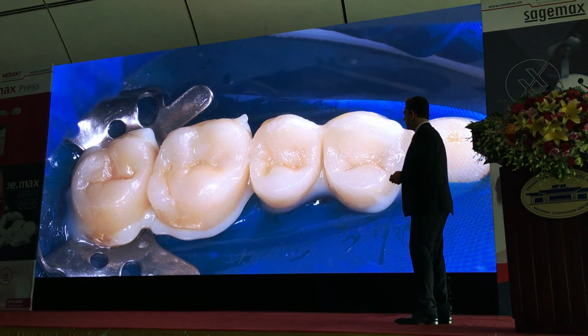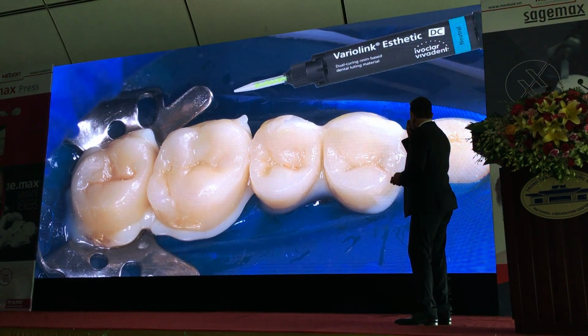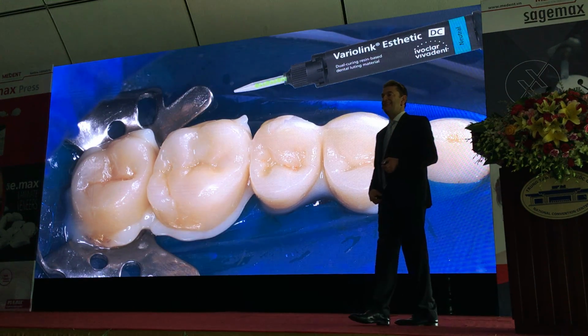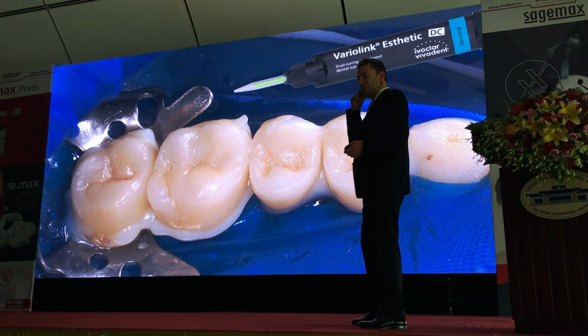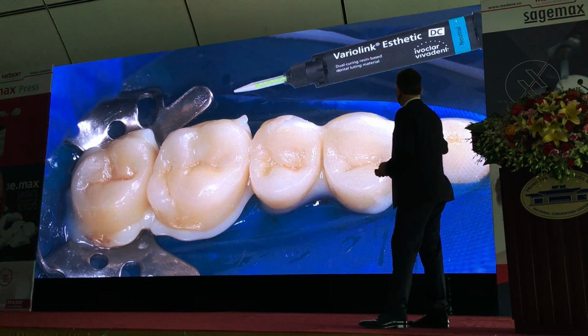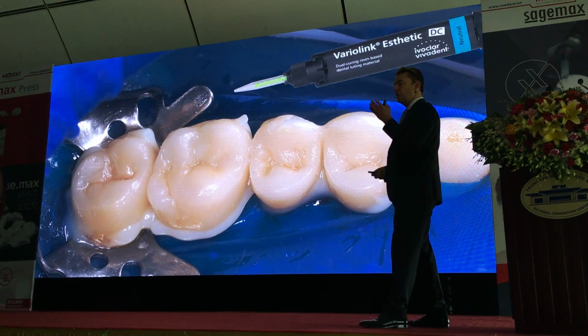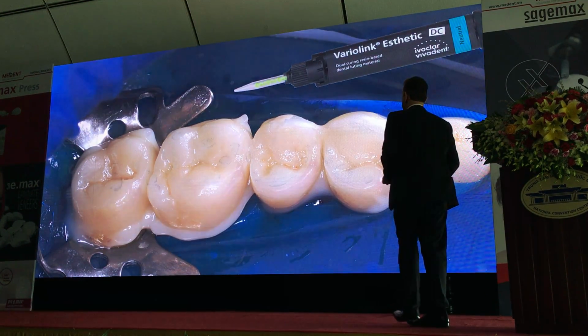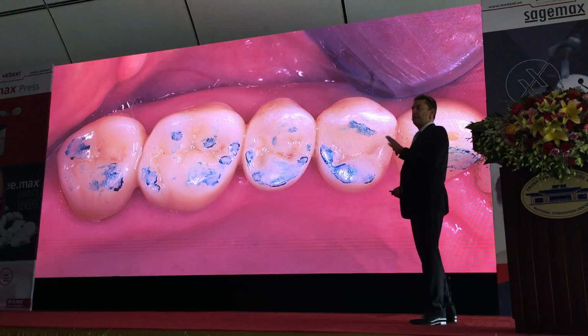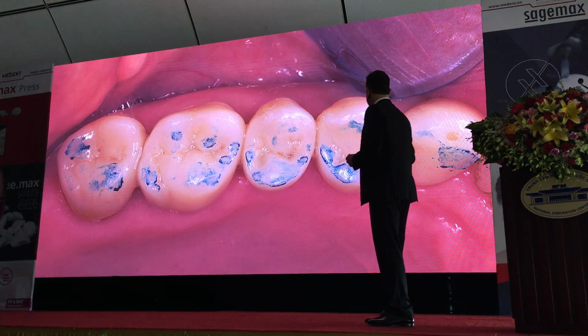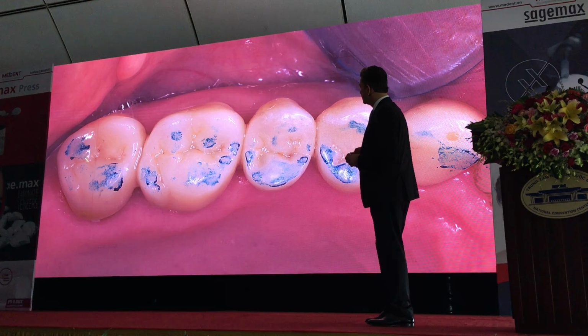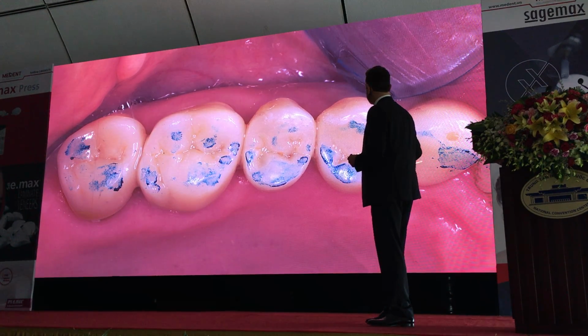So we can now seat the restorations. So here we use Variolink Esthetic. It's called Variolink Esthetic DC, meaning dual curing. Okay, you can see that's the same shade that we have done the try-in. It's the neutral shade, and you can see now we have the excess material. So we need now to remove the excess before we actually light cure it. But I'll show you this step by step. But anyway, we check the contact points. You can see very good distribution of the contact points.